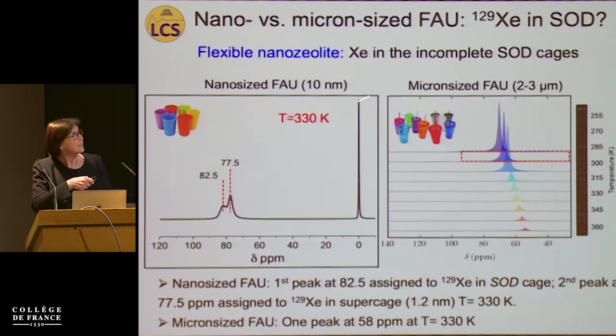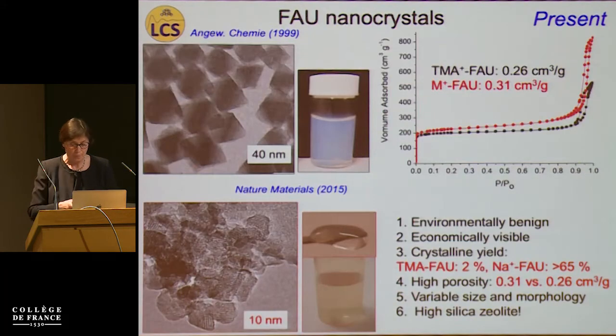We have seen that in the micron-size faujasite, no matter how we perform the xenon NMR investigation, we could see only one peak, and this peak is associated with penetration of xenon in the supercage, while for the nanocrystals, at certain conditions, we could see that the xenon is penetrating the sodalite.